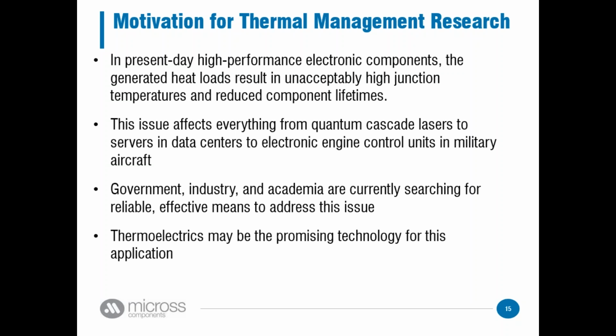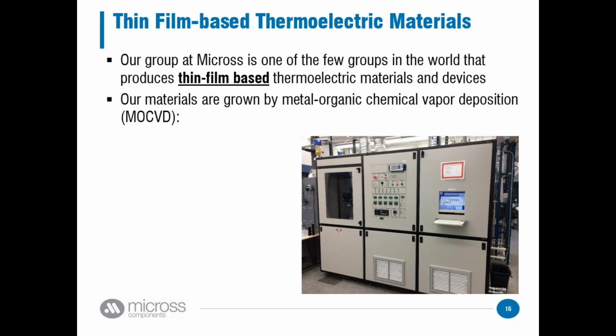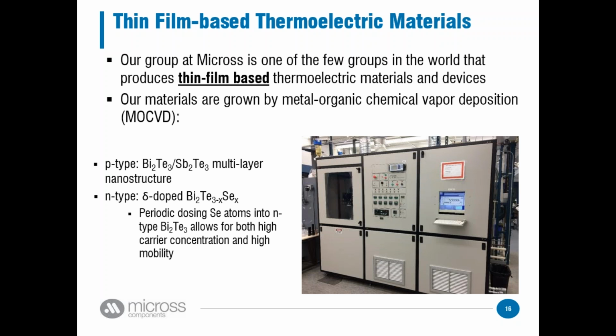Thermoelectrics is one application that could be used. Specifically, the work I did at RTI and which I'm carrying on now at Micross deals with thin film thermoelectrics. I talked to you a little bit earlier about the bulk thermoelectrics that you would buy from Custom Thermoelectric or Marlow or Melcor, where you have thick, millimeter size active layers of thermoelectric materials. What I have here with my materials is I actually grow something more like 5 to 7 to 10 microns of materials. My P-type is a bismuth telluride, antimony telluride superlattice, essentially a multi-layer structure. And I have a delta-doped N-type that behaves similar to a 2D electron gas, where I have high mobilities and high electrical conductivities.